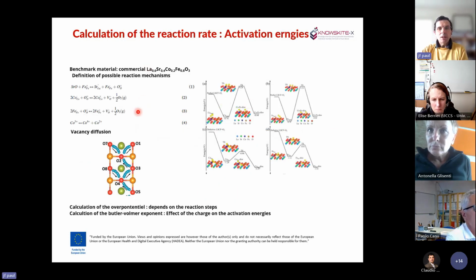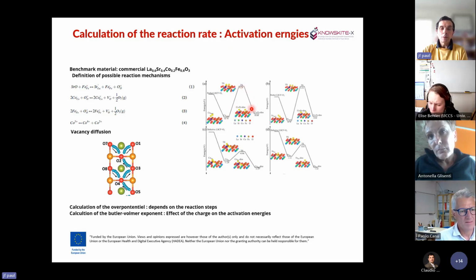So using the same system, people have proposed some reaction mechanism that can be seen here. And once you have a reaction mechanism, you can compute the activation energy. So it's longer than just doing a calculation to get the nature or the vibration characterization of the intermediate, because you have to compute quite a lot of images to completely compute the reaction path starting from the reactant to the product.